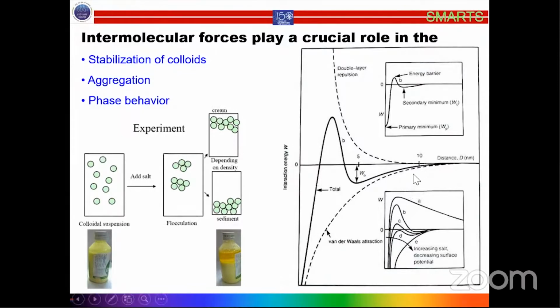And obviously in all kinds of systems you can see the van der Waals interaction at very small interparticle spacing. Typically, if you take a 200 nanometer size emulsion droplet, the van der Waals force is effective when the separation between these particles is less than 10 nanometers. So what you need to worry about is the long range repulsive forces.